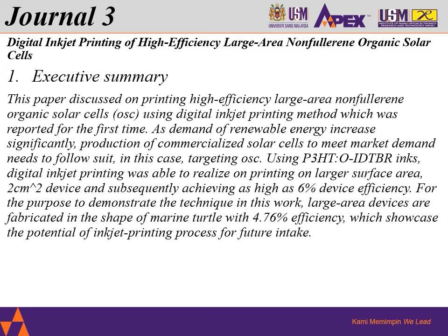So this journal uses P3HT and O-IDTBR, acceptor and donor inks, for digital inkjet printing. The journal reported that using this ink with digital inkjet printing, it was able to print on a larger surface area, 2 centimeter squared devices, and subsequently achieve as high as 6% device efficiency.